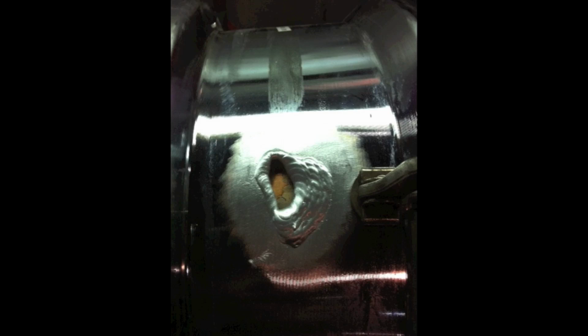So that's the stainless steel hole repair, and the same thing applies on a much bigger hole on aluminum. He's got copper backing clamped on the backside, and it's trapping the argon, and it just takes a little bit longer. A lot more passes, a lot more stopping, and letting it breathe a little bit, but it still works really good. So again, the copper backing on the backside supports the weld metal, and sometimes you don't even have to touch it up on the backside.